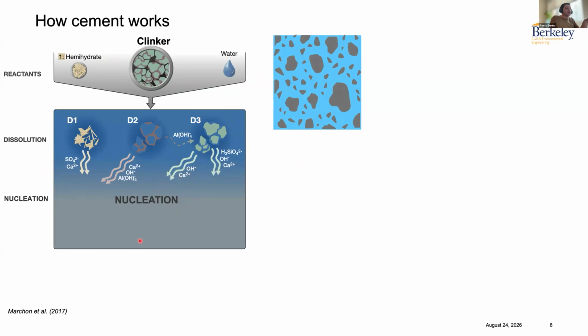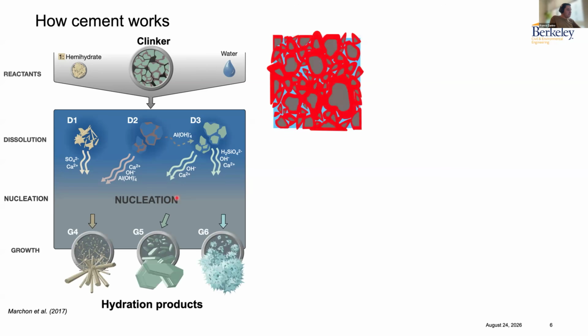And at a certain point in time, we are not going to go into detail on that in this talk in particular, we are going to meet a certain thermodynamic condition of supersaturation that will trigger a process of nucleation and growth of new solids that we call hydrates. And the magic of the process is that these hydrates that form incorporate part of the water from the pore solution into the solid, increasing their volume. So the hydrates are 2 times larger on average than the anhydrous materials.